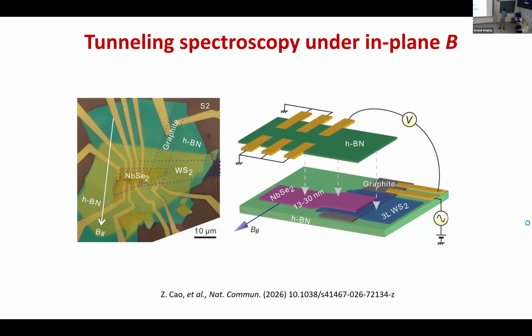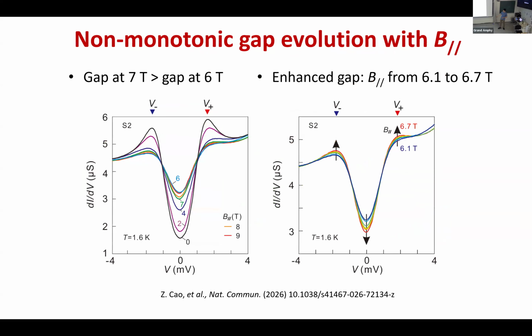Recently, what we did is we fabricated a niobium diselenide sample, and we tried to measure the tunneling spectroscopy by using tungsten disulfide as a barrier and graphite as a metal electrode. And what we see is that when we apply the B field in the plane, from around 6 to 7 Tesla, the gap actually becomes a bit enhanced. If we zoom in here, around 6.1 to 6.7 Tesla, the gap actually becomes stronger. So this is somehow related to the transition.